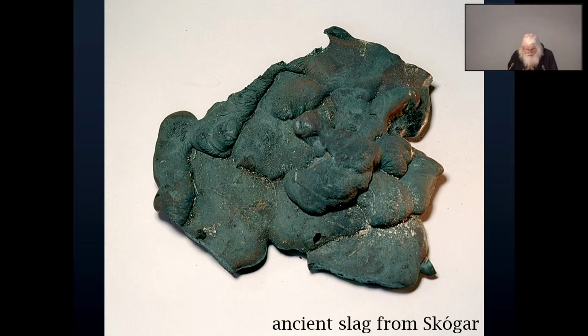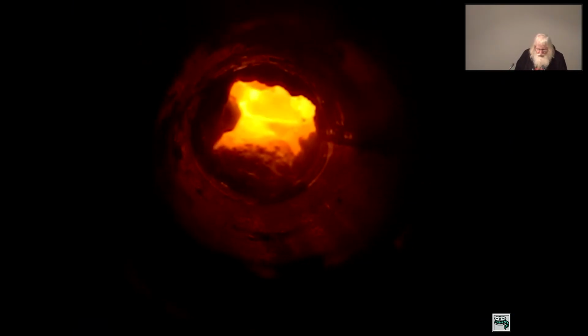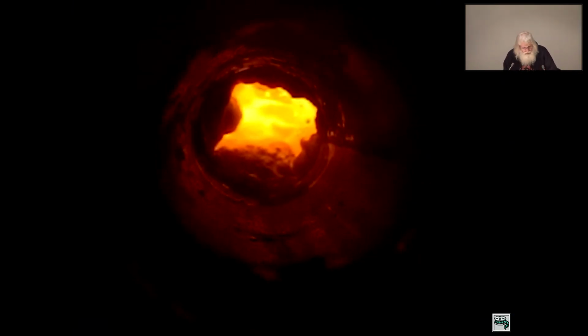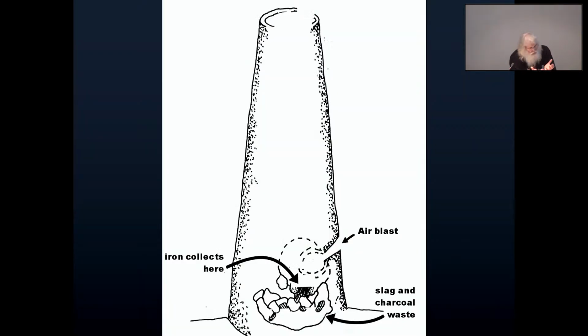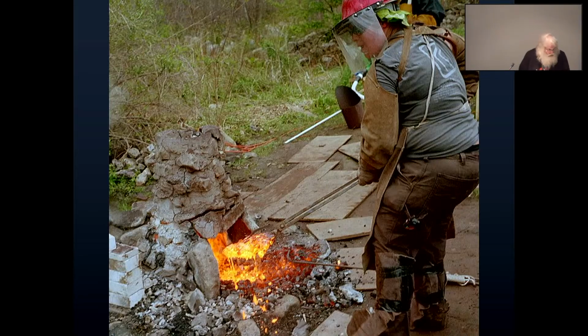Now, inside the oven, the iron is not melted. It's not hot enough to melt it. What we have is solid bits of very, very hot iron that fall through the oven and collect at the bottom in the bowl of slag. And here's what it looks like through a window in the side of the oven. And you can see little tiny bits of pure iron dropping down where they're collected into the bowl. Now, in the bowl, these things don't form a solid structure. They form a spongy type of material called a bloom. And after the process is run, and it usually takes all day, a door in the bottom of the oven is opened and the bloom is taken out.